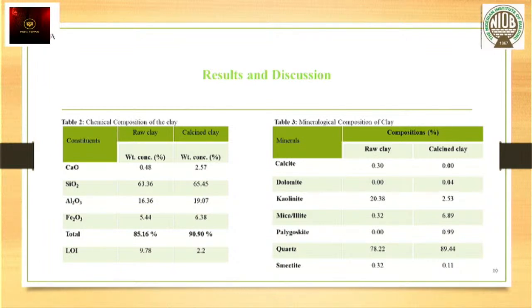the ASTM specification for natural pozzolan, which is equal to or greater than 70%. Also, the loss on ignition was found to be 2.2% for the calcined clay, which is the pozzolanic material blended with the cement, which also met the specification of the ASTM C618 classification for natural pozzolan of not greater than 10% for natural pozzolans. Table 3 shows the mineralogical composition of the clay,